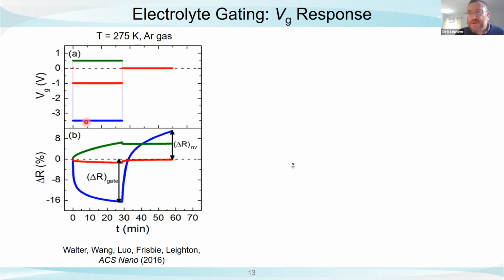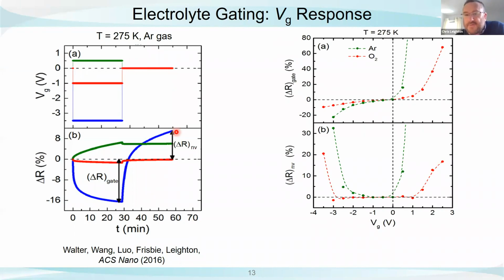But if you go to too large a negative voltage, something like -4 volts, what happens is you get a larger gate-induced resistance change, but when you turn the bias off, it does not recover to the t equals 0 value, but goes to a resistance which is bigger than when we started the experiment. And then different again, if you apply a positive voltage, even a small one, delta R changes sign, you expect that. But when you turn the bias off, you find that it was almost entirely non-volatile. So to track these things versus voltage, we define 2 parameters, this gate-induced resistance change and this non-volatile change in the resistance, and plot them here as a function of gate voltage.